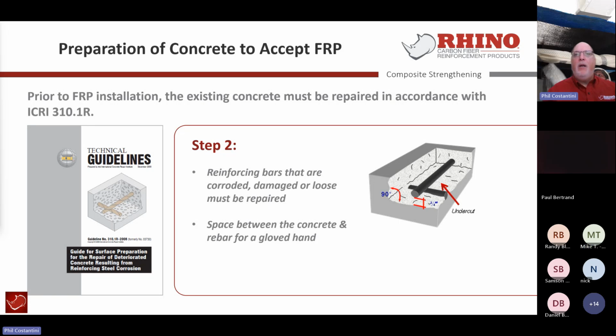Get the rust off there. Use a muriatic acid composition at a 5-to-1 ratio, or a good hydroblast to get it clean, treat it, and then go back and do your typical concrete repair with your structural mortars. For what it's worth, Rhino has structural mortars of various strengths and compositions, and it's important to make sure there's space between bar to bar, so you can wrap around in order to get an efficient structural mortar repair done.